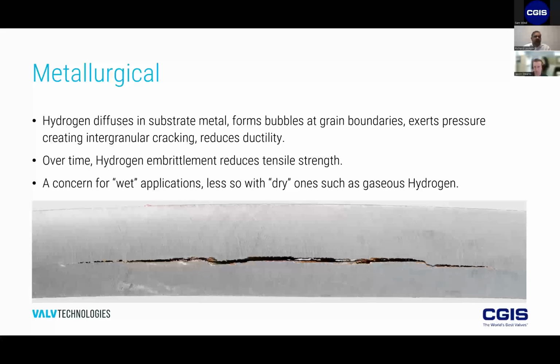Whereas you have water, steam, or gas applications, those materials are generally suited to that application. If it's a very sour application, highly corrosive, then we make sure that there's the right high-performing alloys. But in actual fact, certain high-performing alloys may not be the right thing to use with hydrogen. If we think about alloys such as Inconel, one of the engineers' favorite choices, it may not be applicable to hydrogen because we're concerned about embrittlement.